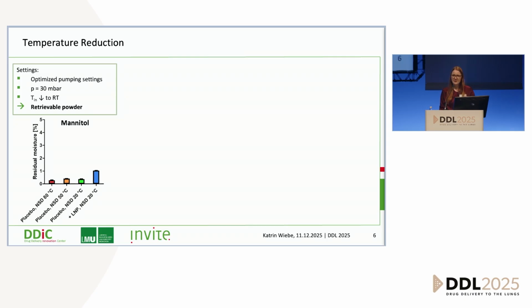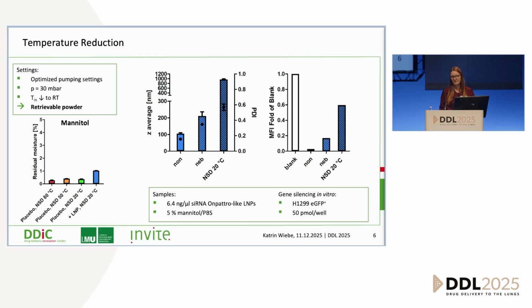So here's where I thought, okay, we have the nebulization down, we have very low temperature, this has to work, and I nanospray dried, and actually it didn't work. We have a huge size increase, as you can see on the left, and the performance in vitro is not very good. The knockdown is only about 60%, and I've repeated this experiment quite some times, it doesn't really get better.